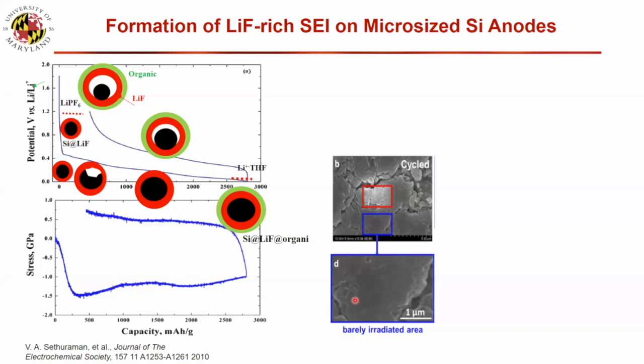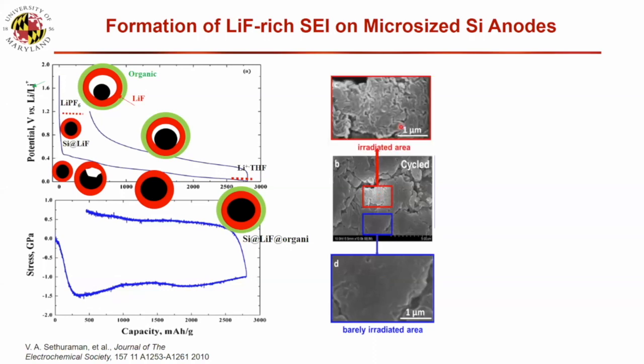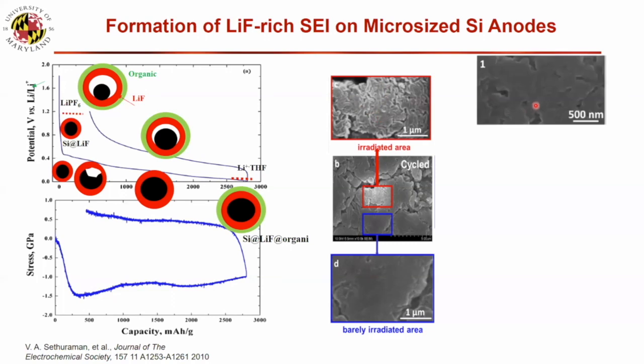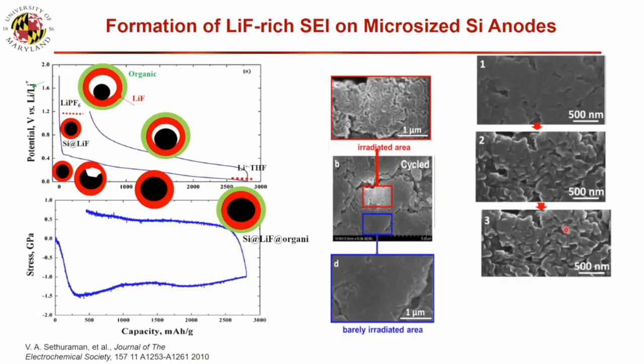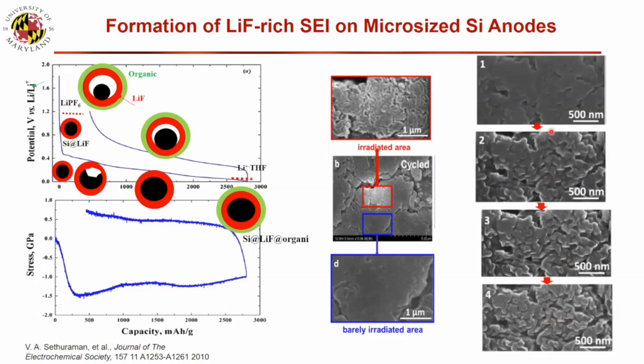at the beginning you cannot see clearly, we believe it's a polymer and a lithium fluoride. If we use the beam a little bit longer, we will see inside, you see the silicon like a flow. More clearly, we just put this slide at the beginning, and continue the beam damage to the surface. We will see it gradually become clear, meaning we decompose the polymer surface and the lithium fluoride, and we really can see inside the silicon flow.